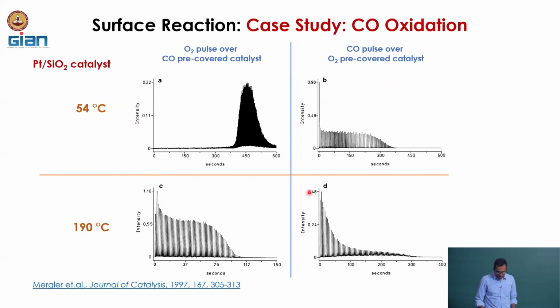Okay. So, now there are certain differences. Let us just start from this one. My surface is pre-covered with oxygen and I am giving CO. So, from the very first pulse, I am seeing the formation of CO2, and that just goes on and then dies out, because the amount of oxygen on the surface will deplete over time. So, we are taking that up with each and every pulse, and that is why my activity goes down.